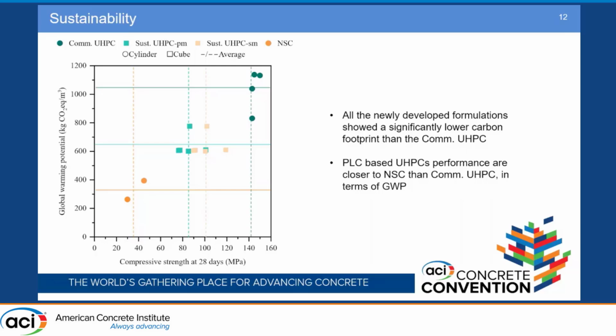And that was the reason why the mixture that had both fibers really benefited from both of these effects. To evaluate the sustainability of our approach, we ran an analysis considering the global warming potential of these mixtures. In this case, we used as a reference different commercial UHPCs that had an average global warming potential that was more than 1,000 kilograms of CO2 equivalent per cubic meter of concrete.